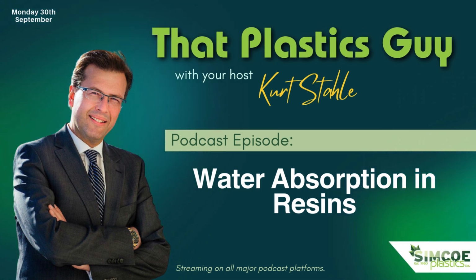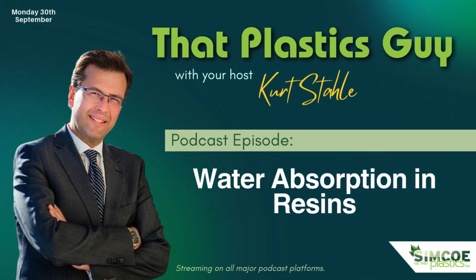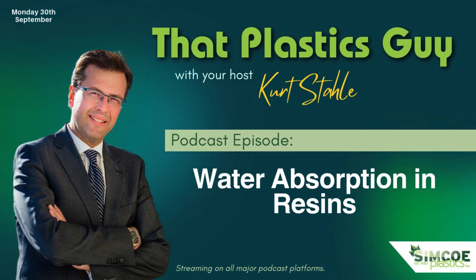So what is water absorption? Water absorption is also called moisture absorption, and it's the capacity of a polymer to literally absorb moisture from the environment into the polymer structure. Absorbed moisture acts as a plasticizer of kinds, so it reduces the glass transition temperature and the strength of plastic.